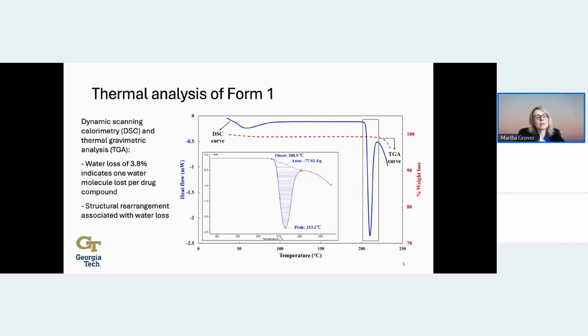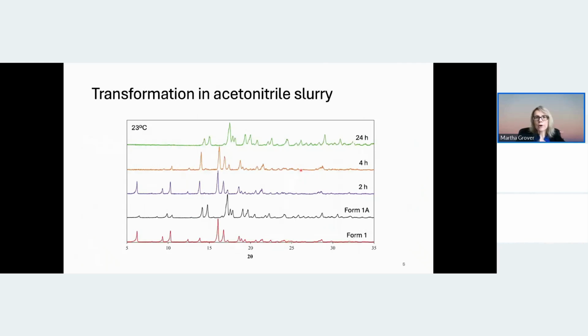So we already had observed that the water was lost from the monohydrate when we had the crystal in vacuum at ambient temperature. We were also able to see a similar transformation when we put the monohydrate crystal into an acetonitrile slurry. Here we have the previous XRD images of Form 1 and Form 1A from the earlier slide, but here I've added the XRD pattern after slurrying in acetonitrile for 2 hours. After 2 hours, there's not really any observable change.